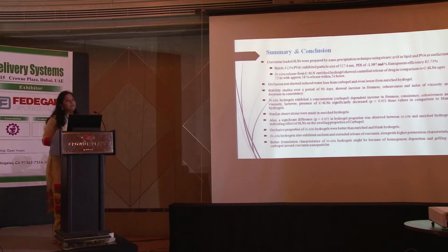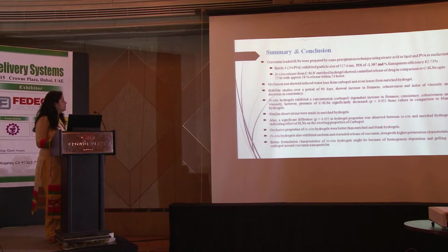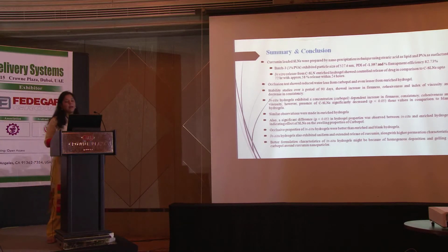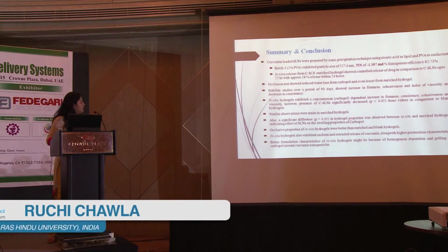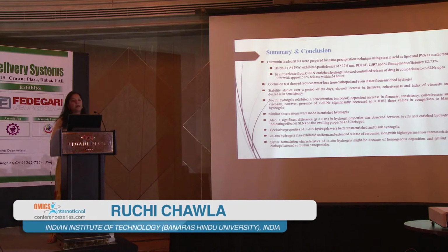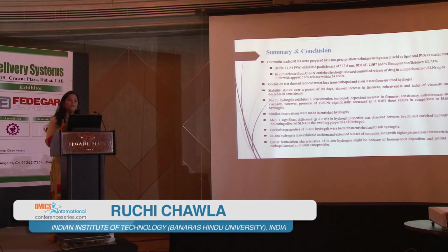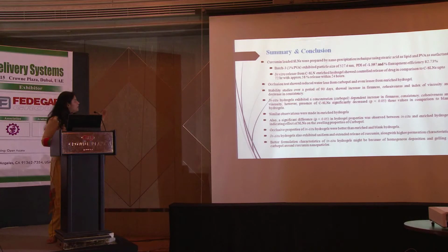So to conclude, it was found that the in situ hydrogels behaved better, might be because of the deposition of the carbopol around the nanoparticles, or the SLNs, basically solid lipid nanoparticles, and the mixture of the already prepared hydrogels with the SLNs was not proper. So the TPA analysis did not give very good results for them.